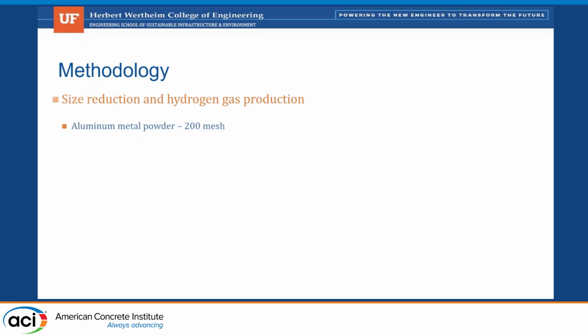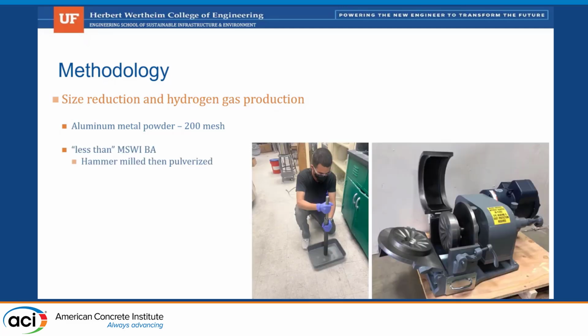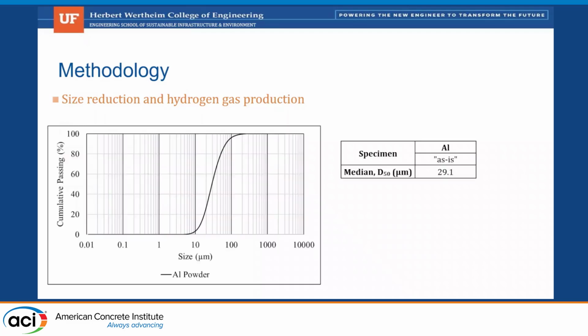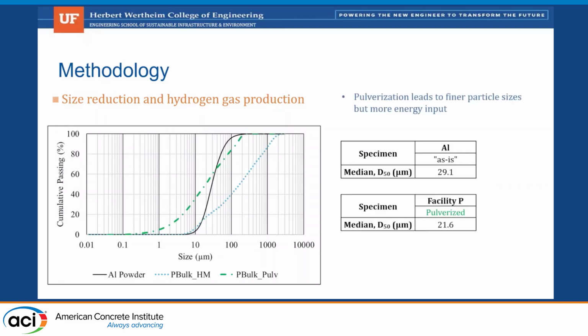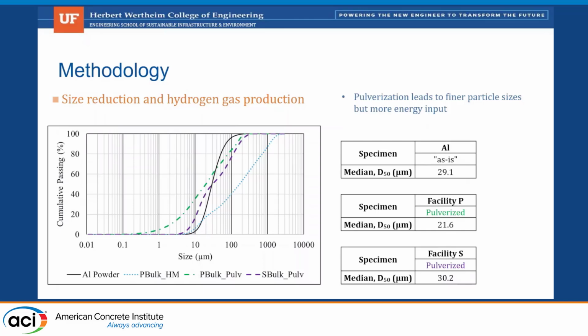And so we took our aluminum metal powder and worked on a comparative test of aluminum powder versus our MSWI ash. We did some solution alkalinity, and I can't get into the hydrogen test in depth today, but we developed a test to measure our hydrogen gas. Again, we have our smaller aluminum particles, and we're looking at the finer fractions, the stuff more towards the left side of our screen, as far as the aluminum and its reactivity.